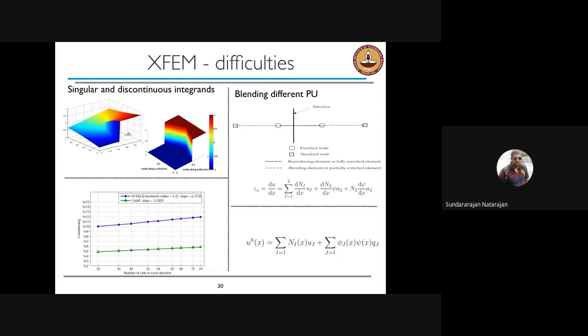The other difficulty is that when we are using local enrichment functions, there will be regions where the nodes are completely enriched, regions where the nodes are not enriched, and regions where they are partially enriched. These are called blending elements in the XFEM literature. The problem with blending elements is that the solution is not represented accurately in those elements, and this leads to poor convergence rates and some problems with the solution. Again, now it is all handled very nicely, so we don't have any blending problem.